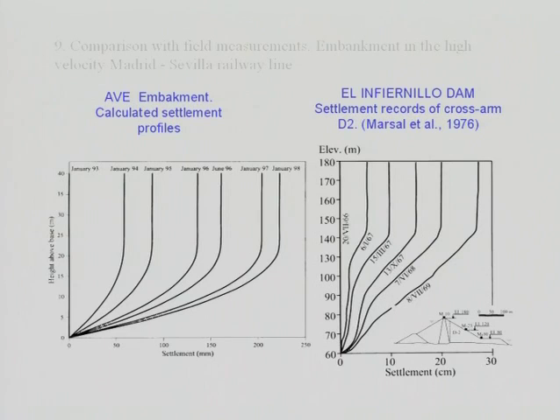You see those are profiles of settlement for different times, and you see that the upper part, the upper 50 meters or so, or no, not so much, 35 or 40 meters of El Infiernillo Dam, at this particular location here, D2, close to the crest of the dam, didn't settle. The settlement comes from the lower part.